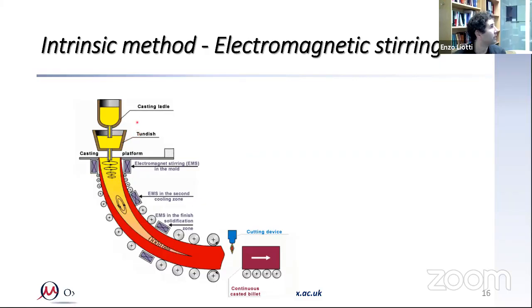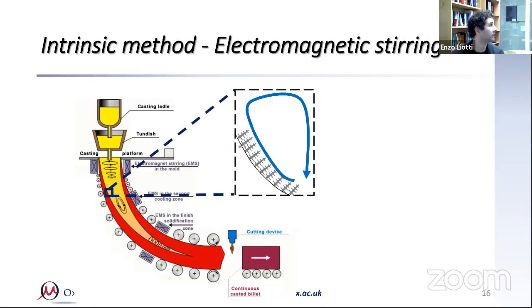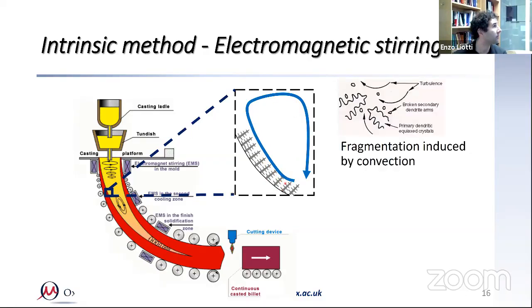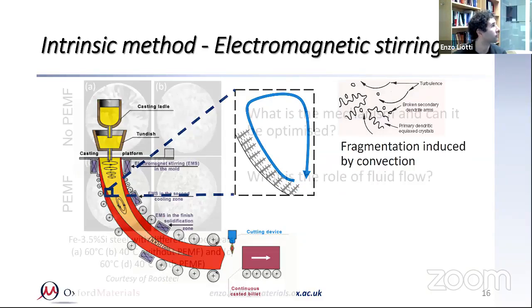This method is already in place, for example, in continuous casting, where along the curve there are several electromagnetic stirrers, normally 2 or 3 here. And if we look in detail, the primary goal of the electromagnetic stirrer is to homogenize the liquid and avoid or diminish microsegregation. But the stirring also leads to the fragmentation and breaking of the dendrite arms, promoting an equiaxed microstructure.